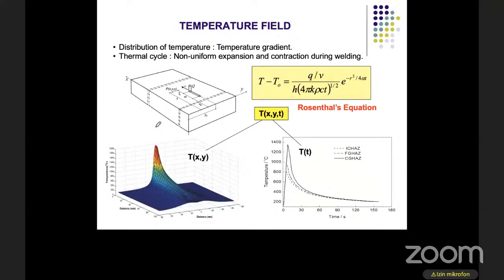The fact is that welding causes local heating, so that it can produce this temperature distribution, in which the weld metal and the area near the weld metal have a high temperature, but in the region away from the weld, the temperature is relatively similar to the ambient temperature. And then from here we can approach using the classical Rosenthal equation, which represents the distribution of temperature and also the welding thermal cycle, something like this.